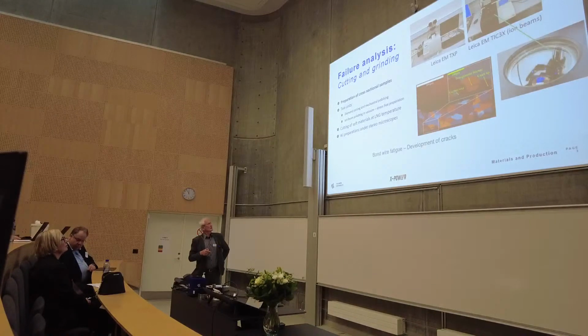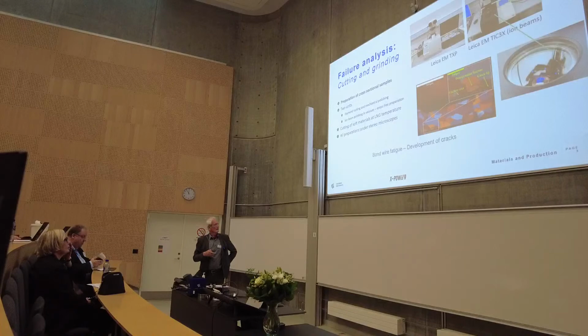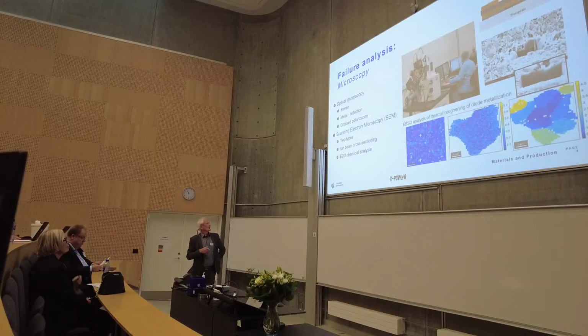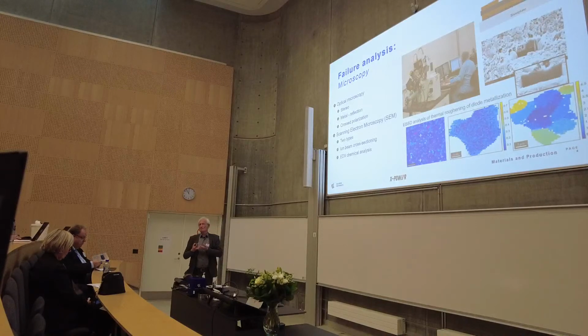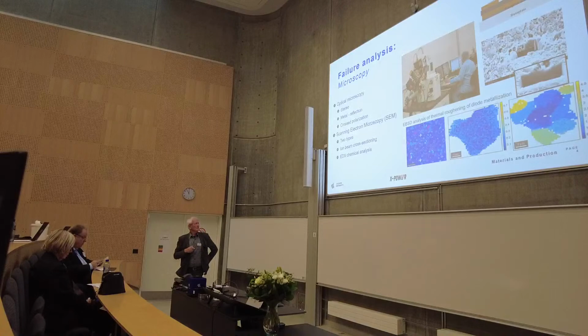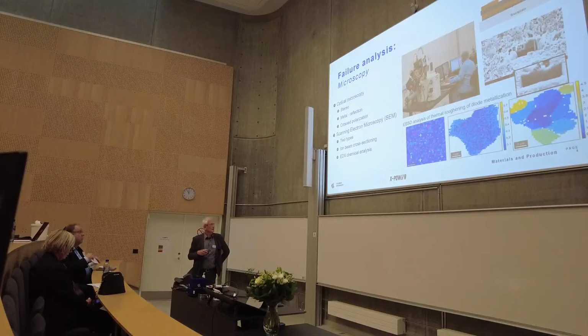The first thing you want to do when you have cut into it is to look at it with a microscope. And this is a microscope image taken with an optical microscope with cross polarizations. This enhances the grain boundaries, or the grains, so you can see contrast between different grains. We have a number of different microscopes. If you want a higher resolution, you go to an electron microscope. We have 2 of those in the clean room.